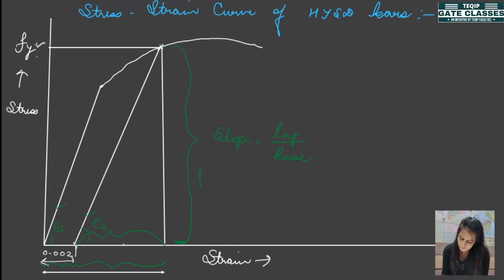So the perpendicular here will be the magnitude of stress and that will be equal to Fy and the base here will be the strain. So this strain will be equal to perpendicular Fy divided by slope, which is modulus of elasticity. So the total strain corresponding to this yield strength of the material will be 0.002 plus this strain and this value of this strain will be Fy by Es. So the total strain corresponding to the yield strength of the material will be 0.002 plus Fy by Es. Okay.